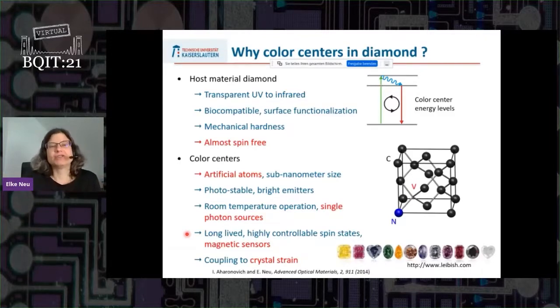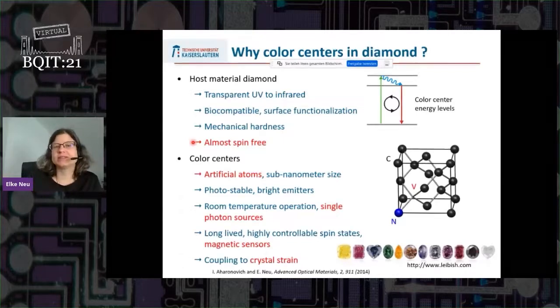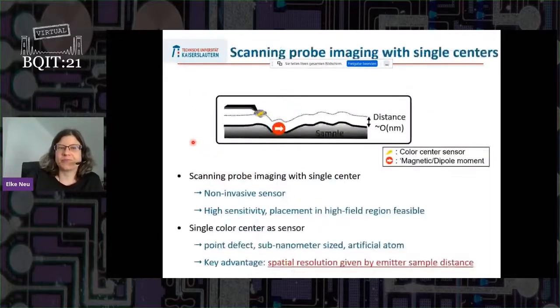Apart from this, I should also say that the host material, the diamond itself, is interesting for us here because it's very transparent. So you can easily extract light from it. It's biocompatible. It has a high mechanical hardness. And if you go into detail, well, diamond is carbon. Carbon is mostly C12, and C12 is a spin-free isotope, so you do not have a lot of spins, and this makes it good as a host for a magnetic sensor.